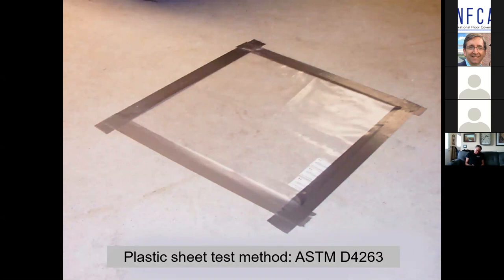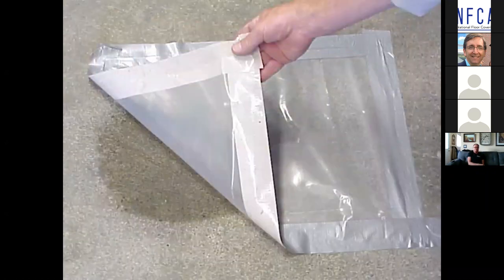Let's talk about the qualitative side. For years, taping down a sheet of plastic over the slab has been used, and it's still a practical method of determining if something is wet or dry. It calls for taping down an 18-inch square piece of plastic, leaving it down for a minimum of 16 hours or longer, coming back, peeling back a corner, and seeing if you see a darkening of the slab or droplets of water on the underside of the plastic. If you see moisture under the plastic, do you put the floor down? Absolutely not. If you don't see moisture under the plastic, do you put the floor down?